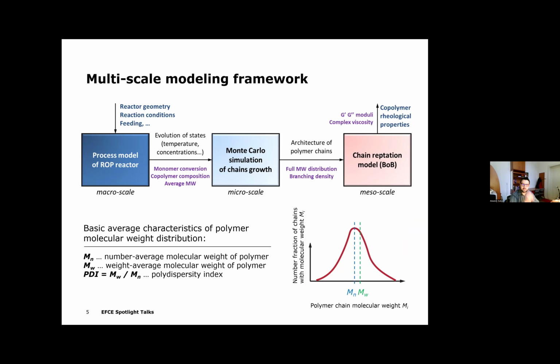So let's start with the multi-scale modeling framework. The whole model that we build here is based on three important parts. The first one we call macro scale or macroscopic or process model. So this is basically a set of ordinary differential equations that look at the reactor as a big vessel, ideally mixed, and using the model we can actually predict the evolution of concentrations of the species that are present in the reactor in time, and also some average properties of the polymer molecular weight distributions, which are number and weight average molecular weight and their ratio, the polydispersity index.